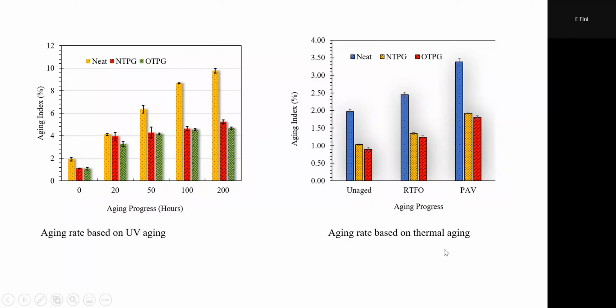The figure on the right here shows you when you actually put the sample under thermal aging, not UV, not ultraviolet, which is solar, right? The one on the left is representing solar degradation when the pavement is sitting out under intense summer sun. And the one on the right is showing thermal aging. So when we do a short-term, RTFO is representing short-term, PAV representing long-term aging.